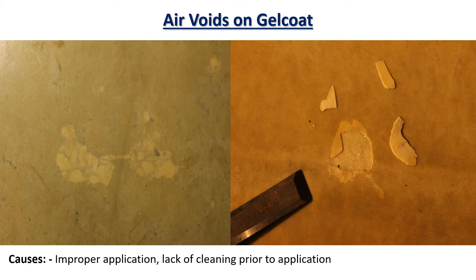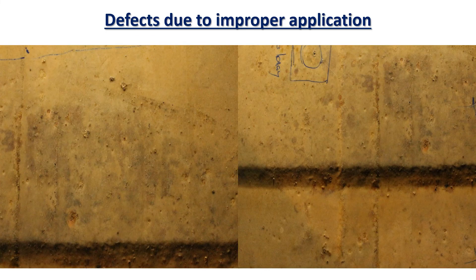These are the main GRE lining defects we can observe in crude oil tanks and other chemical storage tanks. Here you can see some GRE lining defects due to poor application. We can see a lot of contaminants and dust particles inside the lining. Before cleaning, the final gel coat was applied above those contaminants. This creates poor bonding between the layers, and sharp dust particles or contaminants open the top layer of lining, allowing the product to enter into the underneath layers.